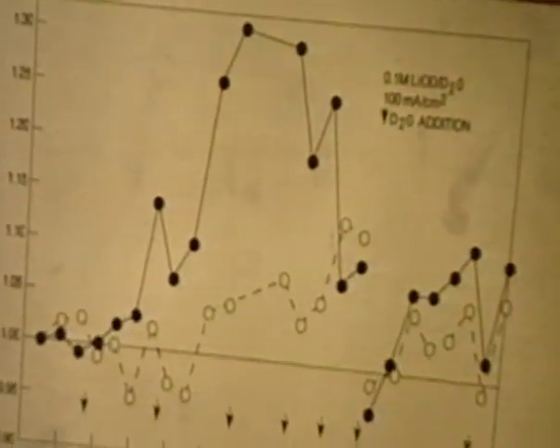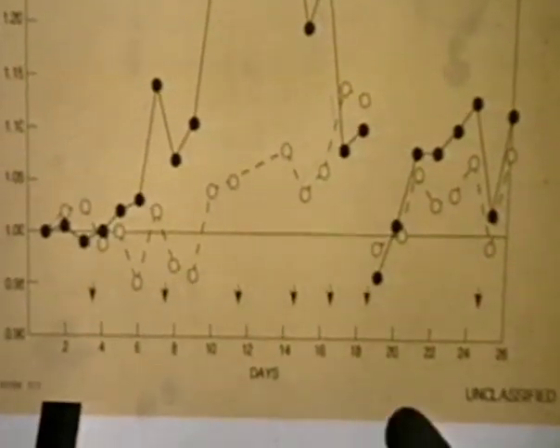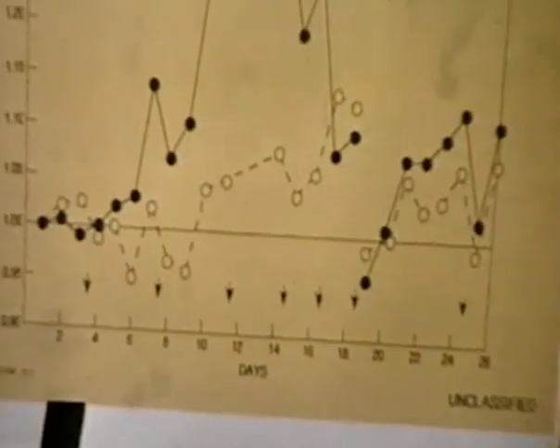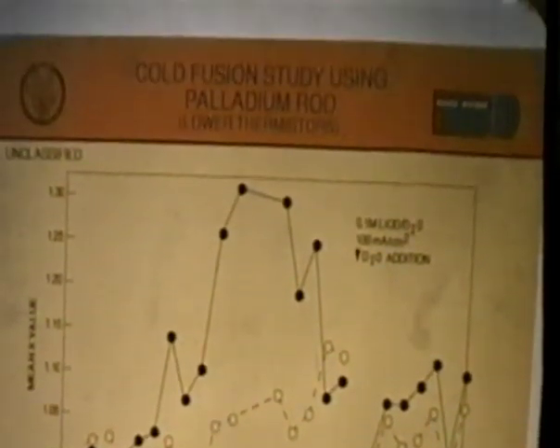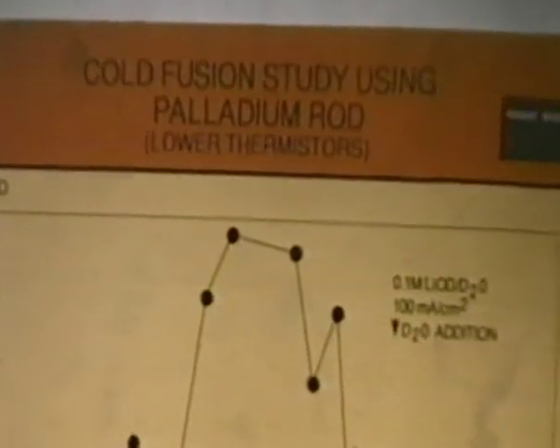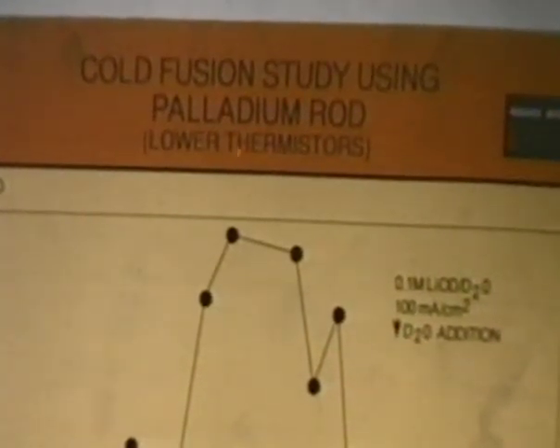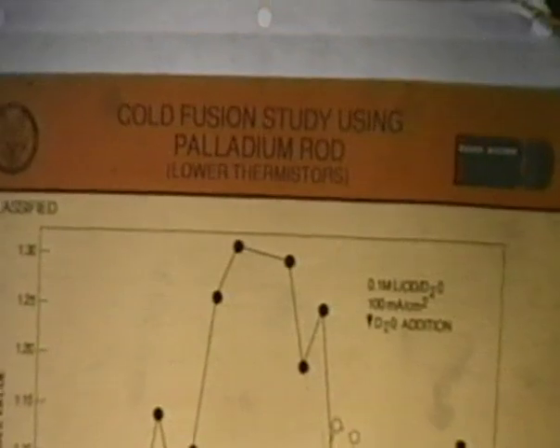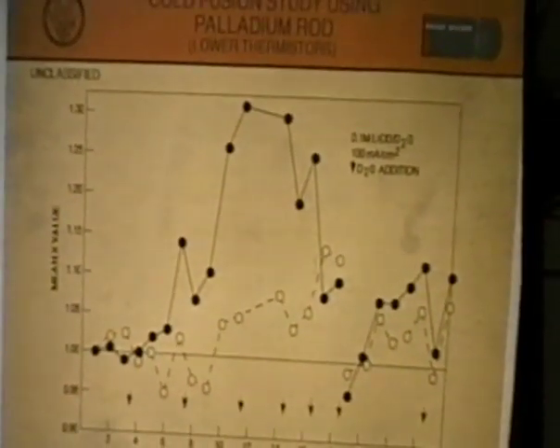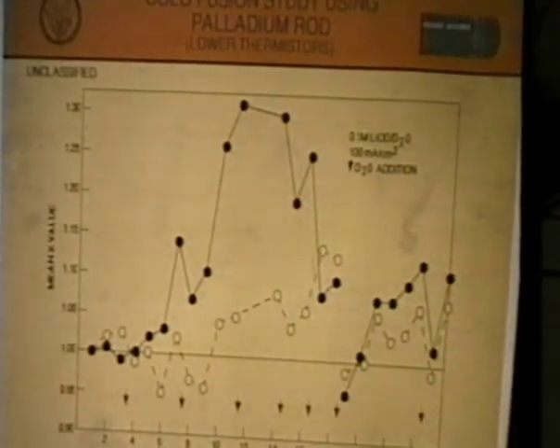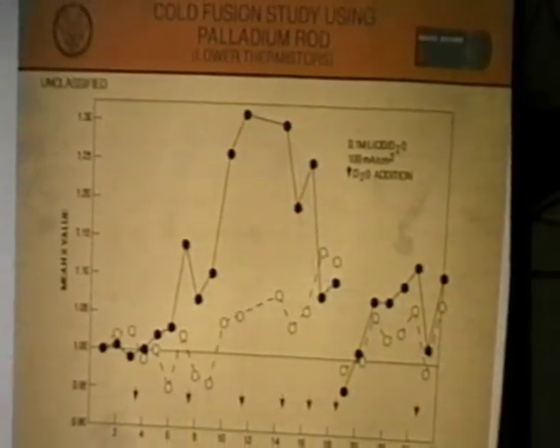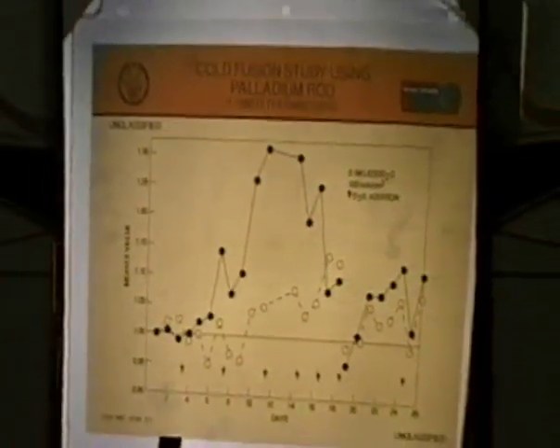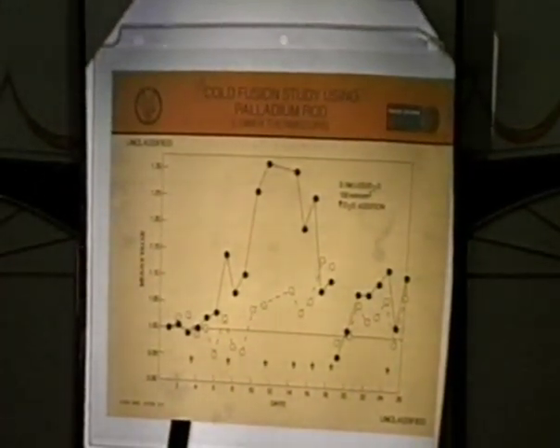Eventually, we got a new source of palladium from Johnson Matthey in about September of 1989. We'd been using this older palladium up to that point and never saw excess heat, but with the Johnson Matthey material that was about 6.35 millimeters diameter, we did see excess heat for the first time after about 6 days. We got as high as 30% excess heat. This is the ratio of heat out to heat in. So we did get up to 30% excess heat.